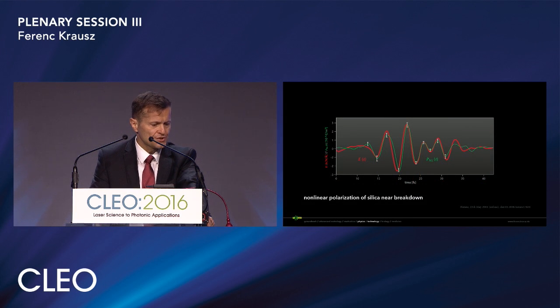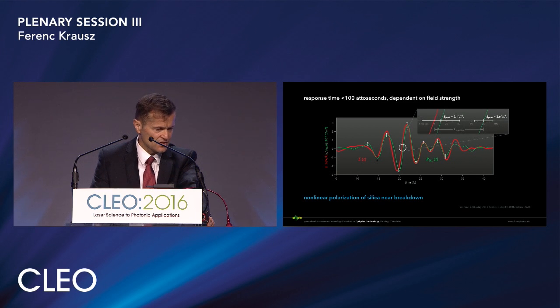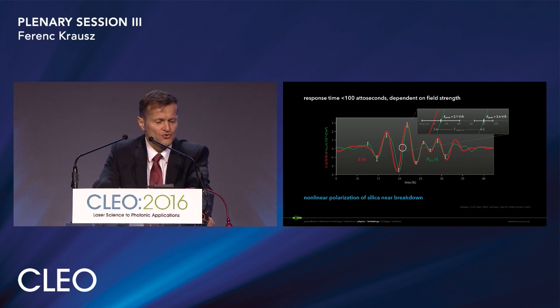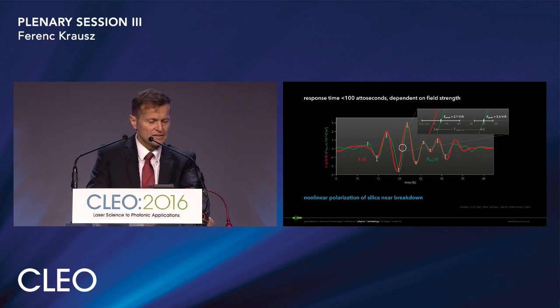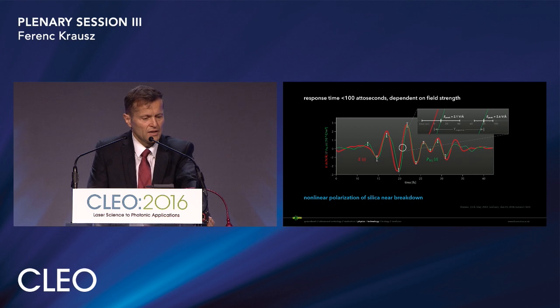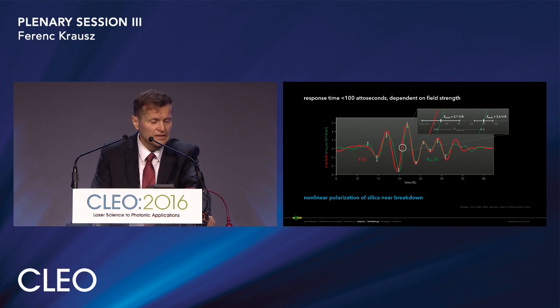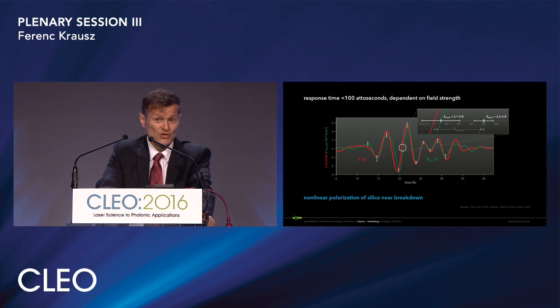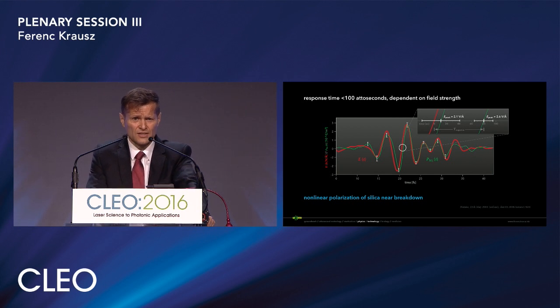Here you see the measured nonlinear polarization of silica near breakdown. And you recognize that it is slightly lagging behind the driving electric field by less than 100 attoseconds, which, quite remarkably, is dramatically dependent on the electric field strength. It decreases very, very rapidly if the field strength is decreased, in this case, from 2.6 volt per angstrom down to 2.1 volt per angstrom. Equally remarkably, this delay turns actually negative by the trailing edge of the pulse.